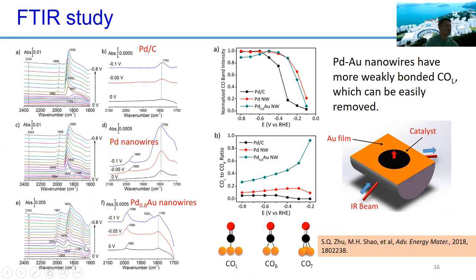If you use palladium gold, then this trend is even more profound. At low potential, you can see that the top CO is actually very clear. If you integrate the intensity of the CO bands and take the ratio of top bonded CO to bridge bonded CO, you can see that for the palladium gold nanowire at the same voltage, the linear or top bonded CO has a much higher percentage.